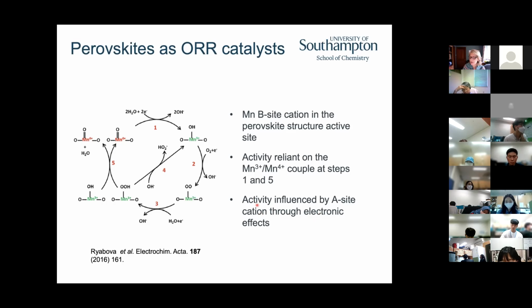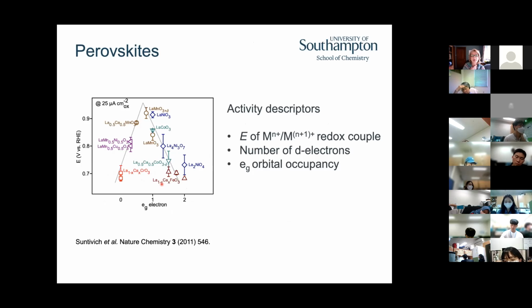And that activity has been shown to be influenced by which A site cation you choose. And that A site cation may be lanthanum or calcium, while cobalt and nickel here are the B site cations. So if we're looking at the manganates, we might have a mixture of lanthanum and calcium, and other mixed species. But we find that the lanthanum manganate itself, when it's a little bit oxygen deficient, provides us the best material.